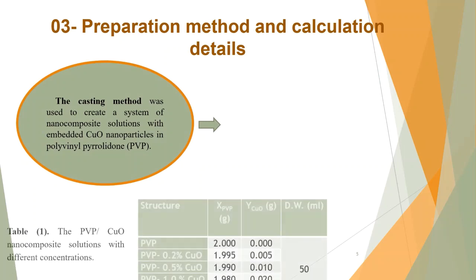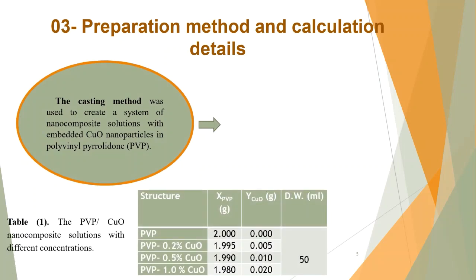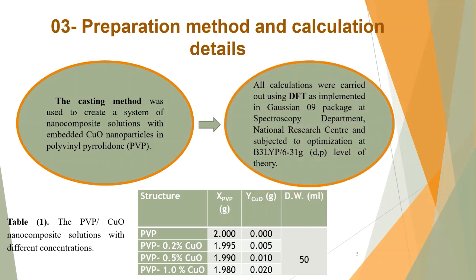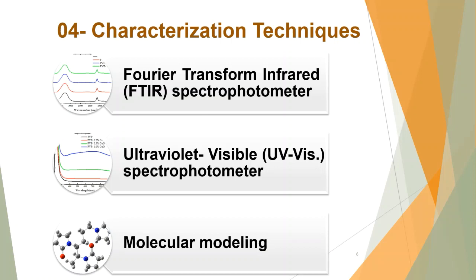For the experimental work, the nanocomposite solutions based on PVP and copper oxide were prepared utilizing the solution casting method according to this table. However, all the calculations were carried out utilizing density functional theory as implemented in Gaussian 09 package at Spectroscopy Department, National Research Center. The prepared nanocomposite solutions were characterized utilizing FTIR spectrophotometer and UV visible spectrophotometer, and finally molecular modeling.